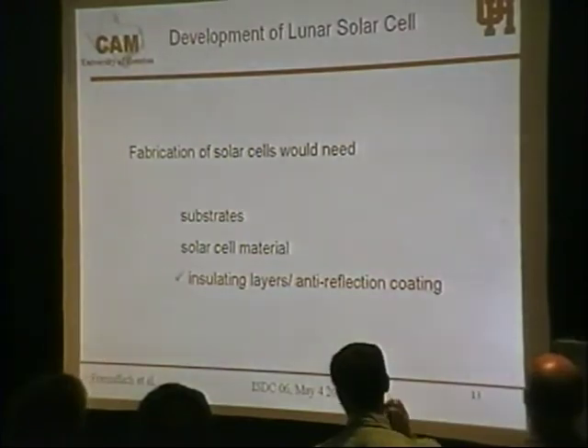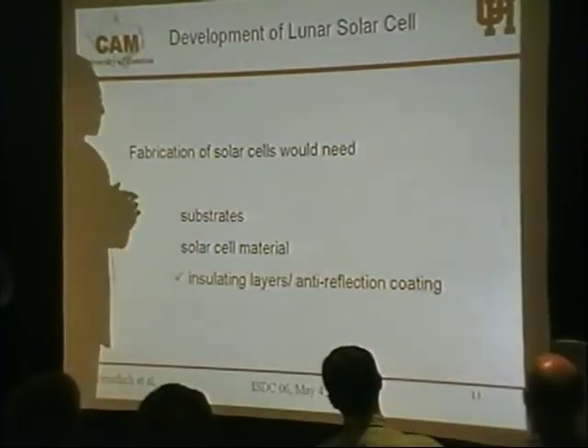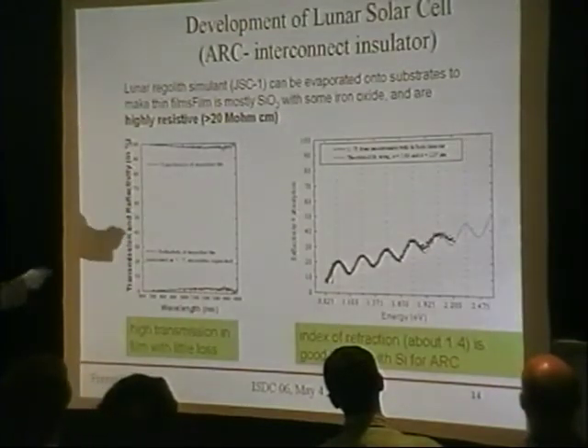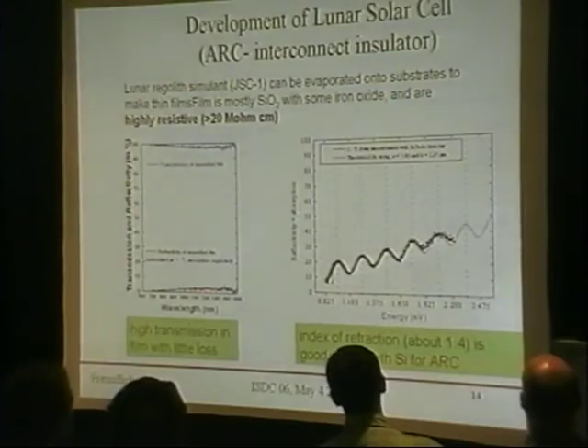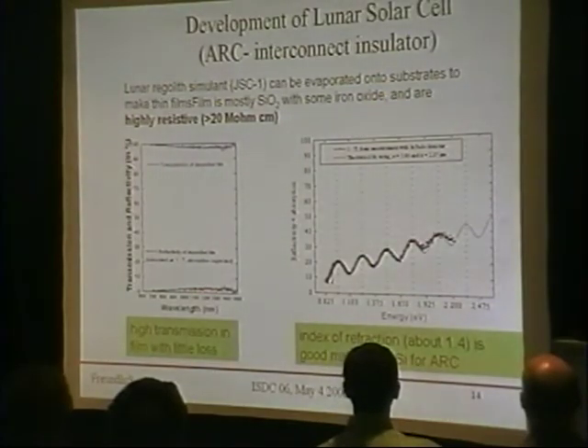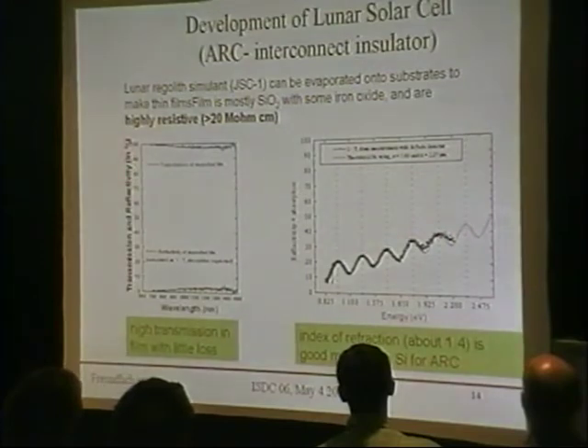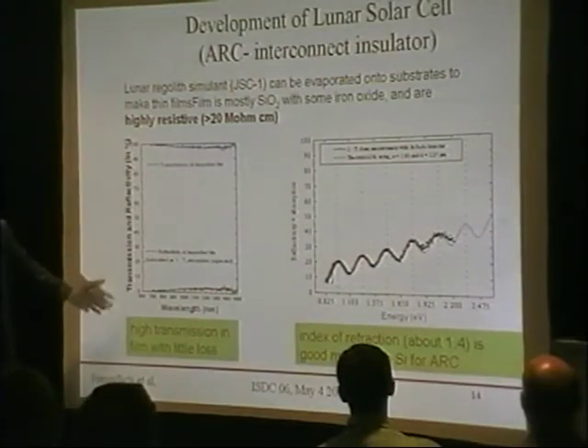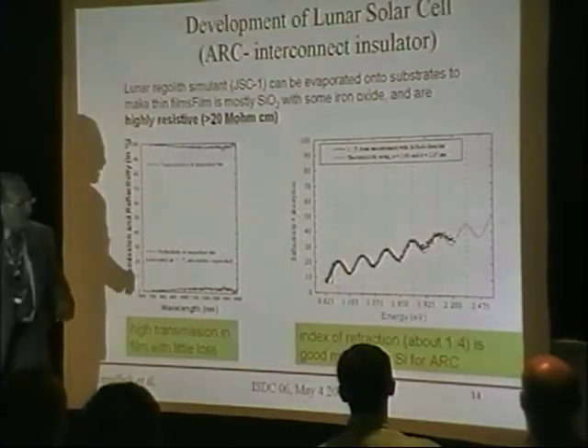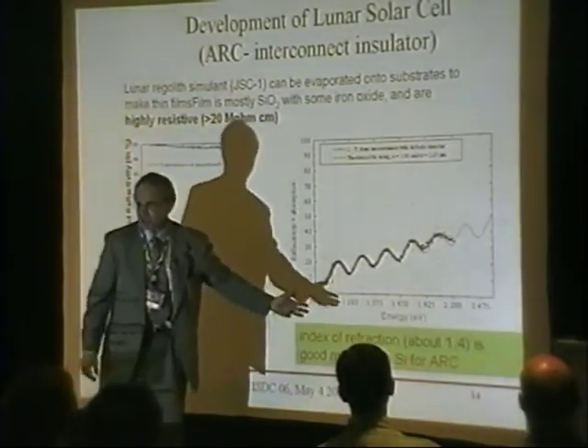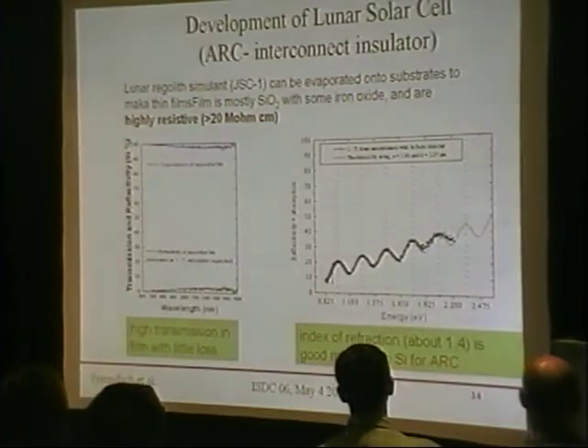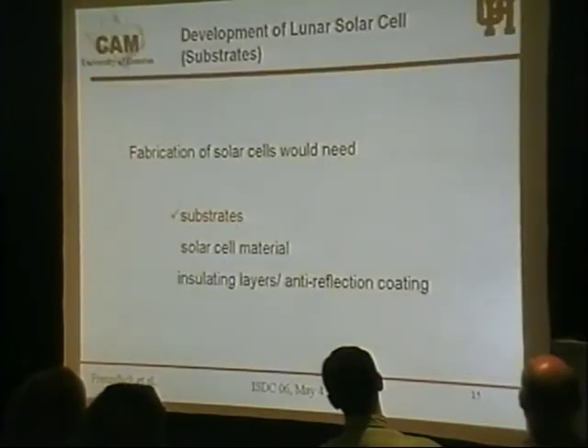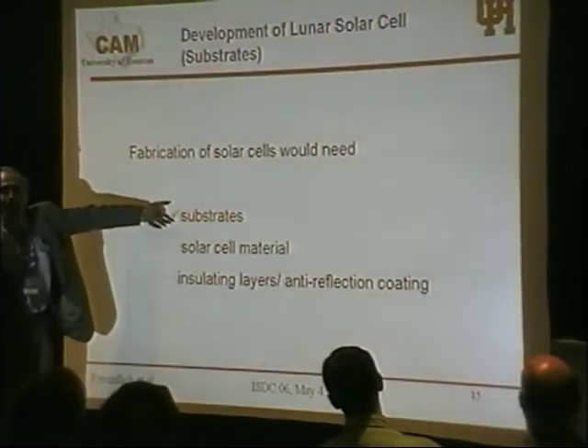The insulating and the anti-reflective coating end up being the same. Essentially, we took JSC-1, which is a simulant of the lunar regolith, and we evaporated JSC-1. Through that evaporation process, JSC-1, which is very close to anorthite, gives you a mixture of aluminum and silicon oxide. Relatively high resistivity, very high transmission, so it's not going to shadow your solar cell if you're using it on top. And also an index of refraction, as expected, that's very close to the mixture of silicon oxide and aluminum oxide.